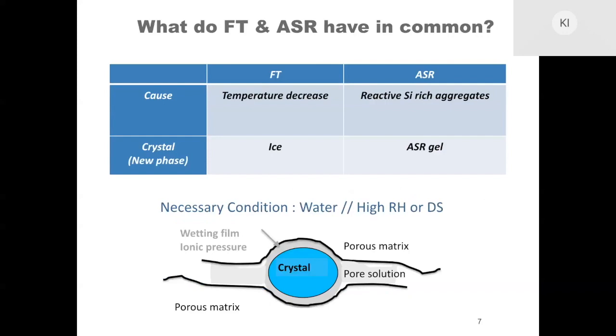In the alkali-silica reaction, we have a gel phase. So it's a soft phase. And actually, it's a problem of solidification, as we can say better, instead of crystallization, because it's not always a crystalline phase. But what is very important in both cases is we need to be saturated with water. So basically, one of the key problems is where the water is, how the water is distributed inside the pores of cement, and how it is causing the damage.